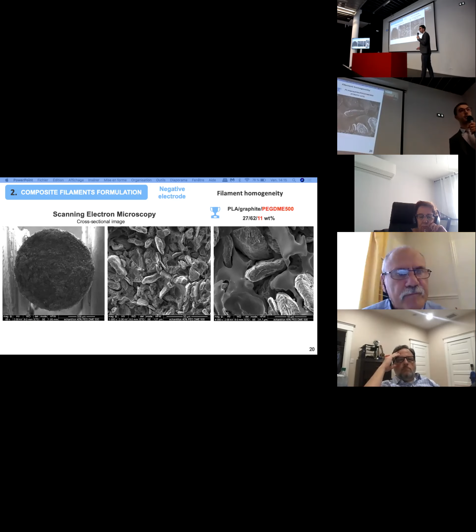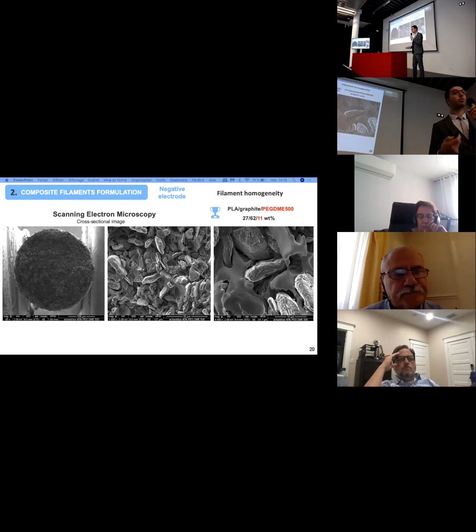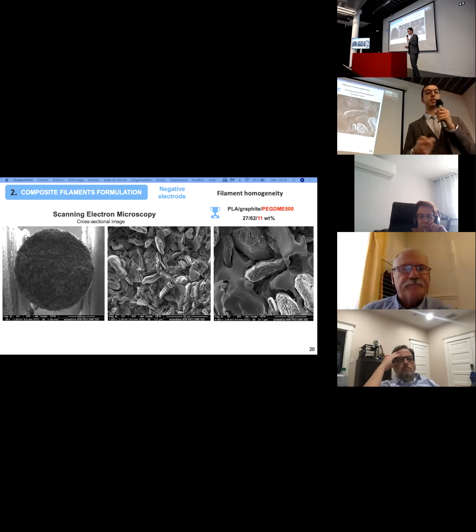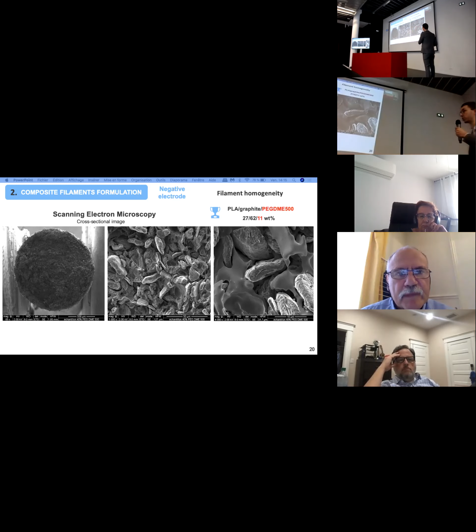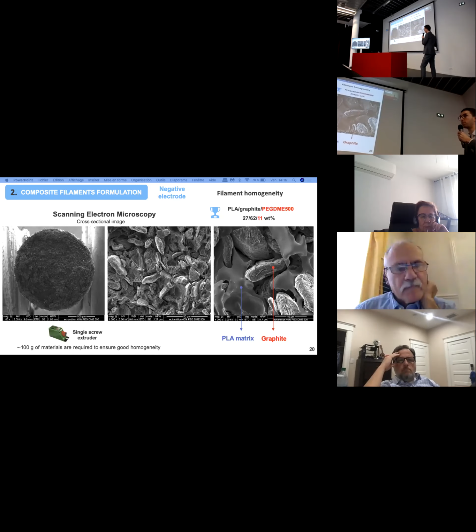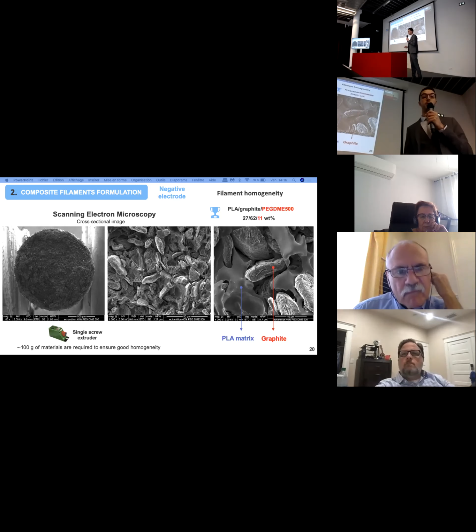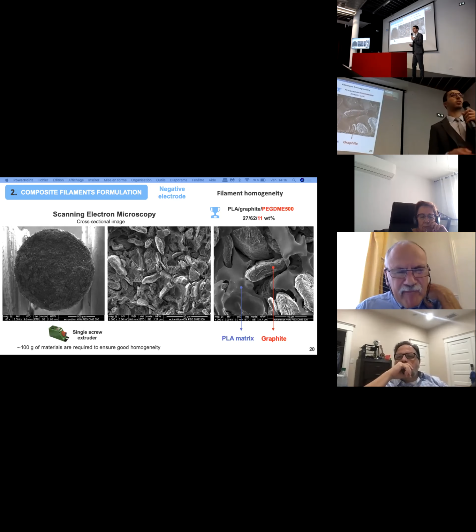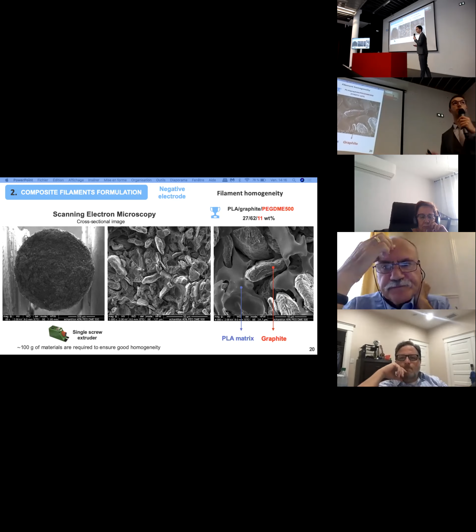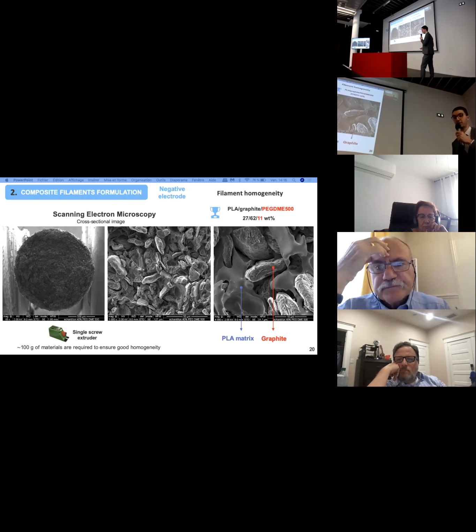Of course, it was necessary to take a look at the filament homogeneity. So we have done that thanks to scanning electron microscopy. And so here, for the resulting optimized composition, you can clearly see that the graphite flakes are really well distributed in the PLA matrix. Nonetheless, it's really worth mentioning that in order to have such a homogeneous filament here, up to 100 grams of materials was required in order to ensure good homogeneity. And this is particularly time consuming.